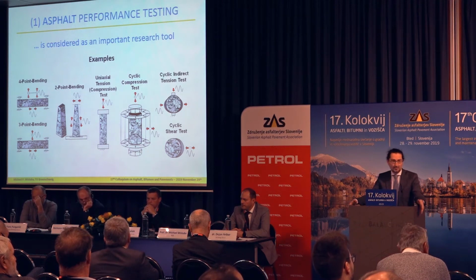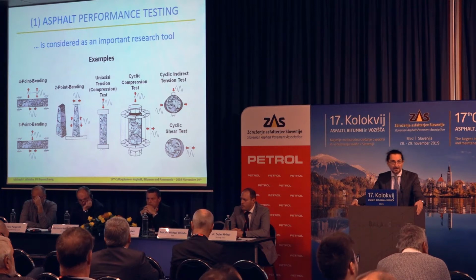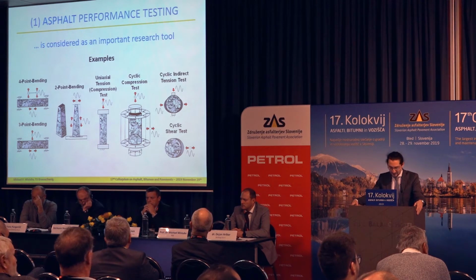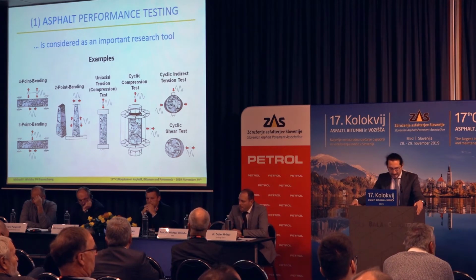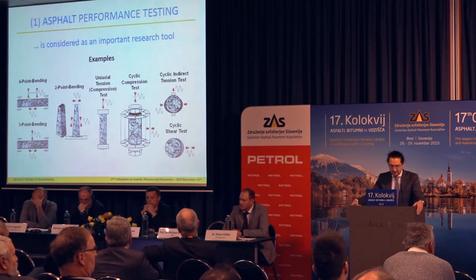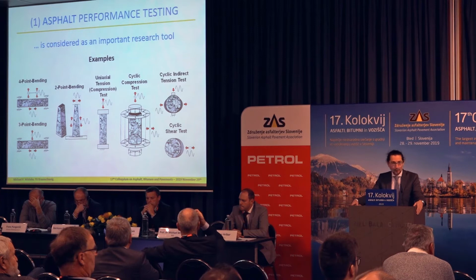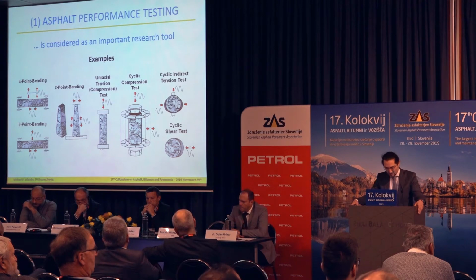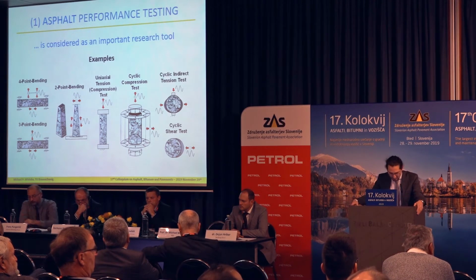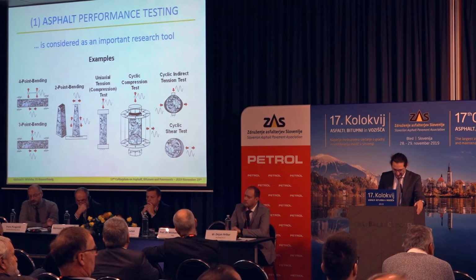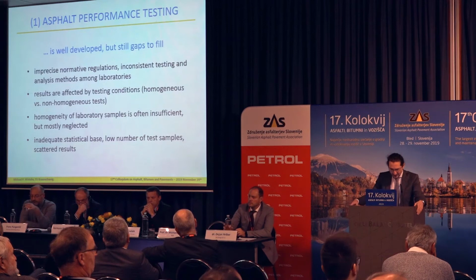So first point, performance testing of asphalt mixtures means that we try to simulate what is happening in the road using asphalt mixture beams or asphalt mixture cores from the road or produced in the laboratory with laboratory mixing and compacting equipment. And as you can see on this slide, which shows some examples, the world of asphalt mix testing is rather complex. We use different techniques and we use different specimen shapes and geometries, and also very complex shapes like, for instance, the 2-point bending beam, which is really tricky to produce.